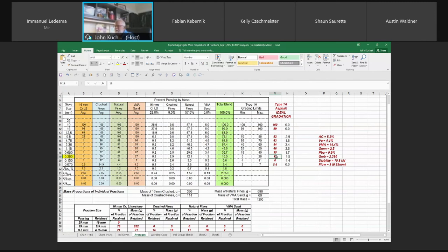And that's why we come up with an 1.18. That's why we're not shooting for down the middle. We want to be a little finer there. So if you're close to 18, all the better. These can be out a little bit more then. Not a lot, but these are the ones I would shoot for that are critical: 475, 075, 0.3.